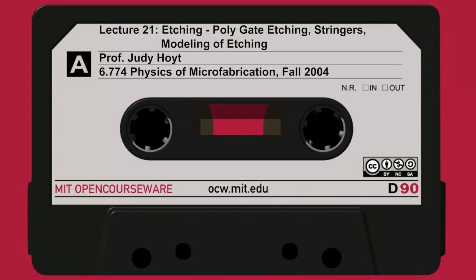How do I get rid of it? Well, you say just keep on etching. Keep going to do an overetch. So even though I've finished etching the poly gate and I'm done in this region, I'm not done over here. So you keep it in and you keep banging on the top of that stringer until it finally goes down to 0.